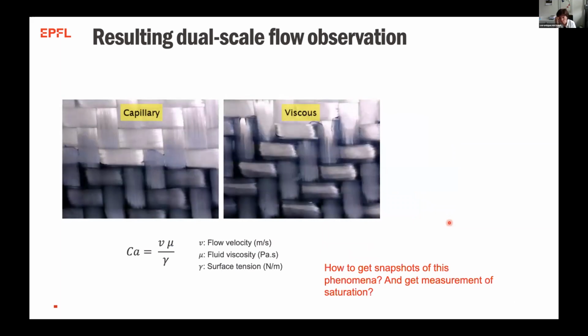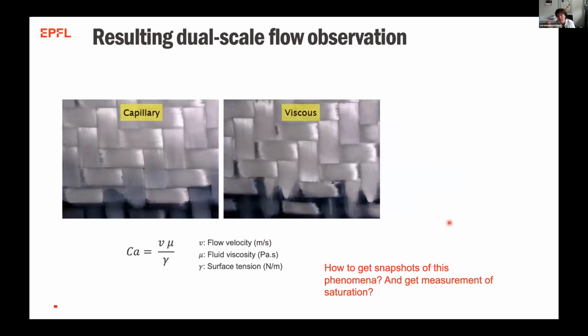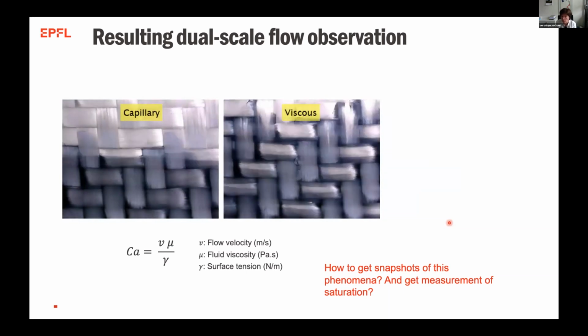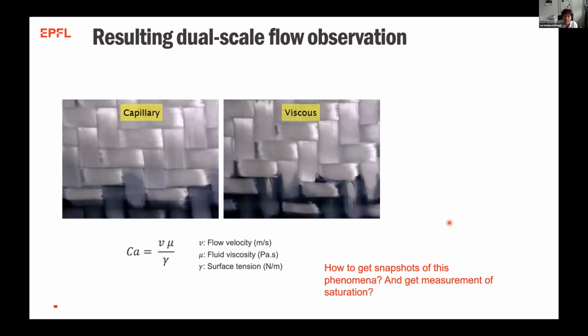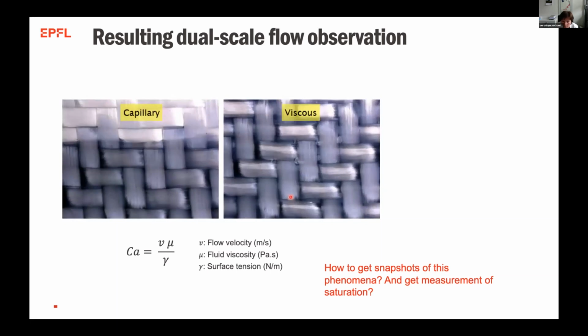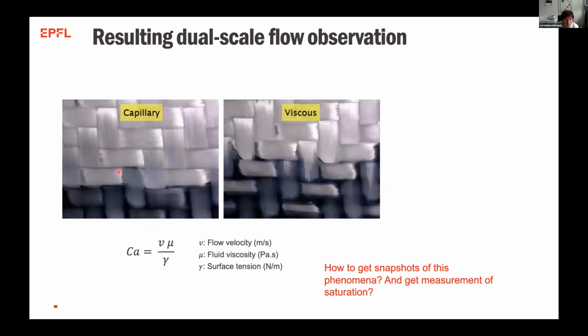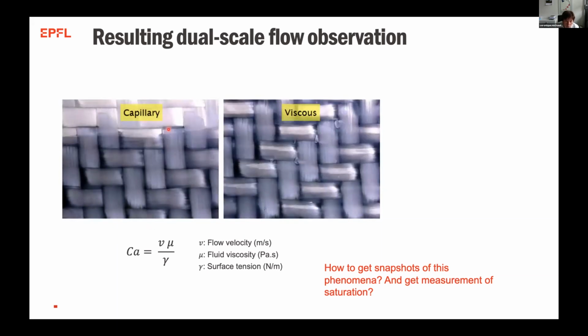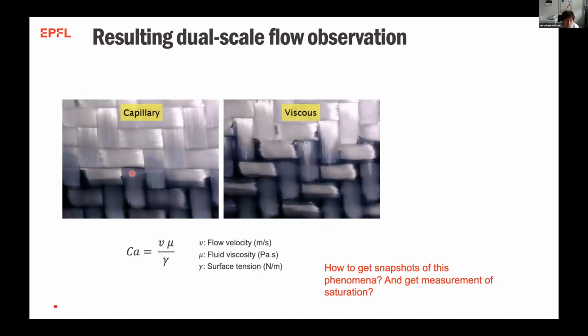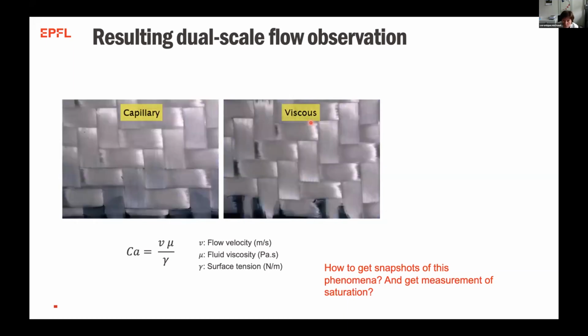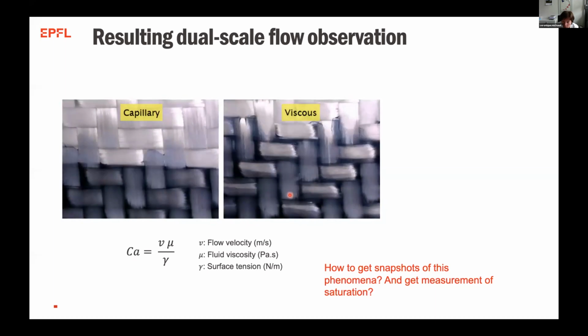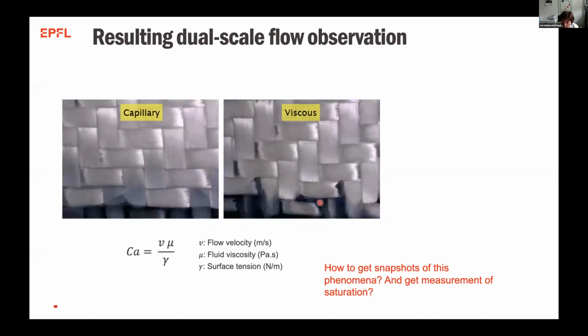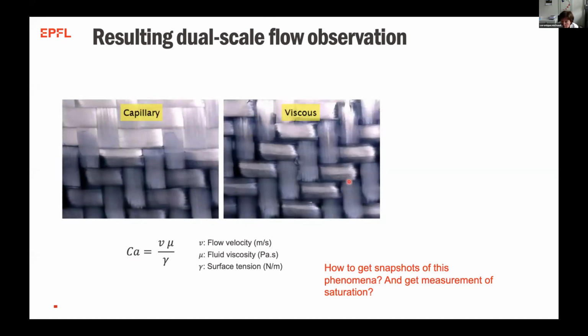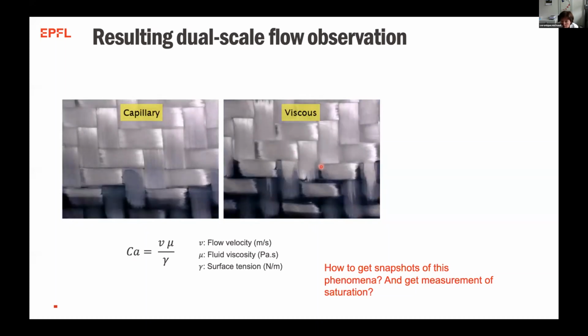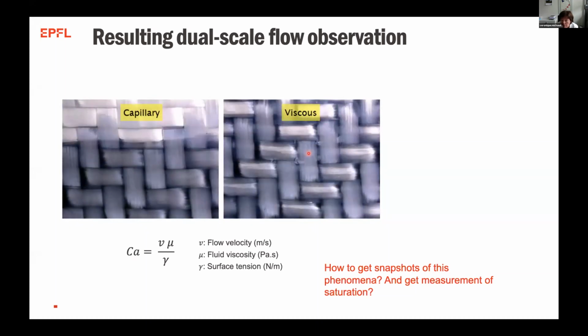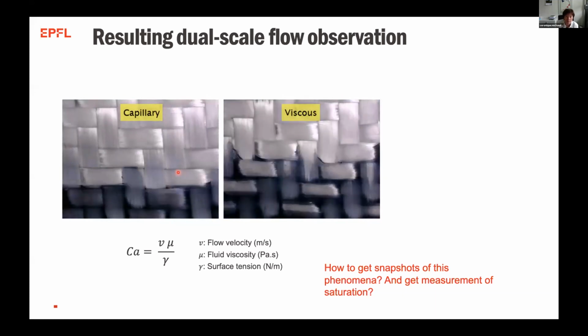So now, of course, it's interesting to see what's happening, because in what was observed, a lot is in the final part. Now, if I want to see, if I stop here, I cannot stop it. But here I have a capillary driven flow, and you see that it's really driven here. And here I have a viscous driven flow, and you see that it lags behind, and these guys will finally... and you see a lot of pores also taking place everywhere that are being filled up and so on.